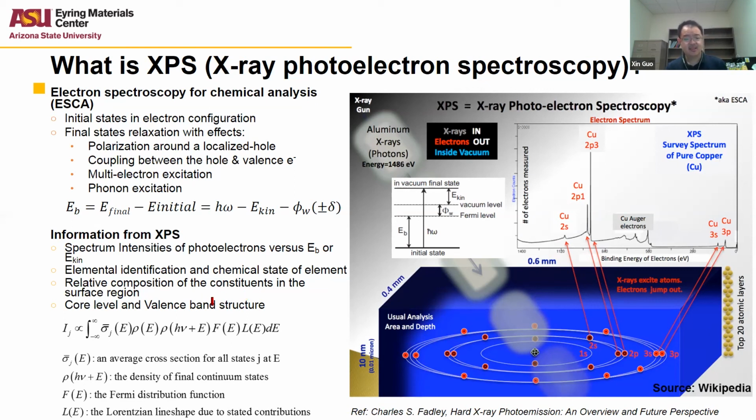So how could we do this? For valence band structure, we need to know the density of states within the valence band range. The photoemission intensity is proportional to the integral of this equation: the average cross section for all states j at energy level E, times the density of states for electrons in the initial configuration, times the density of states in the final continuum states. Those terms are multiplied with the Fermi distribution function that describes the probability of finding an electron in a certain state